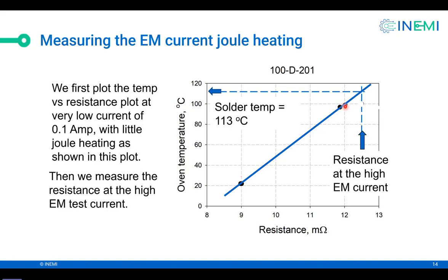So in this case, for example, this dot at 100 degrees centigrade was a low current, and we pumped high current. The temperature increased by about 11 degrees. So 11 degrees is Joule heating. So we can do this on every specimen. So we know exactly what the solder temperature is during electromigration.